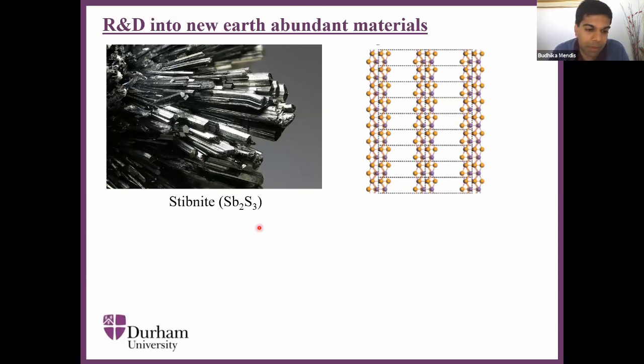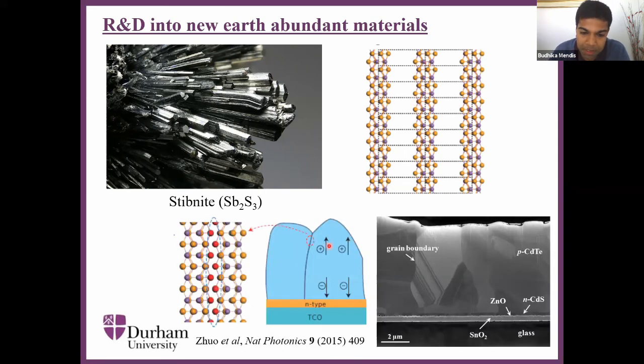This is a compound of antimony. This is stibnite. The crystal structure of stibnite is interesting because it consists of these 1D ribbons. So unlike your traditional solar cell devices, the charge transport, if you like, is one-dimensional, taking place along the ribbon direction. And what that means is it provides a pathway to overcome some of the defects such as grain boundaries, because if you imagine that these ribbons are stacked in the vertical direction, then the charge transport is taking place up and down the thin film, and it avoids the deleterious grain boundary regions. So stibnite is one material that is being researched at the small-scale R&D level.